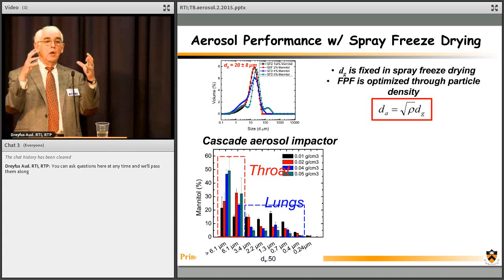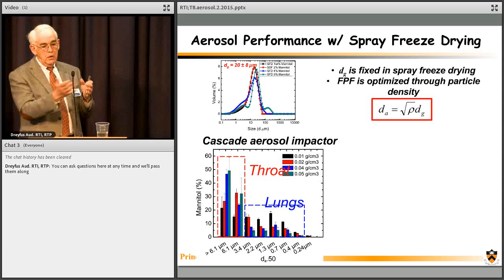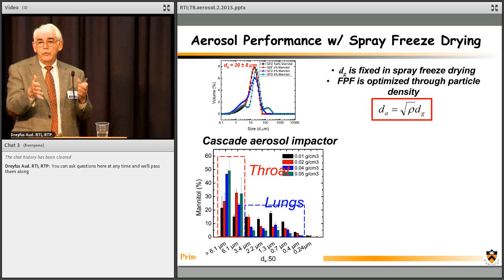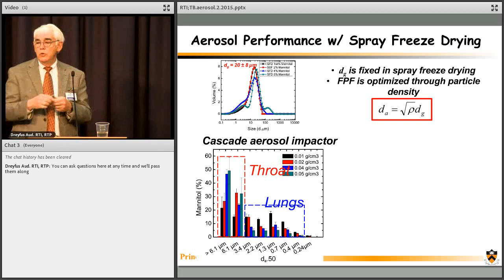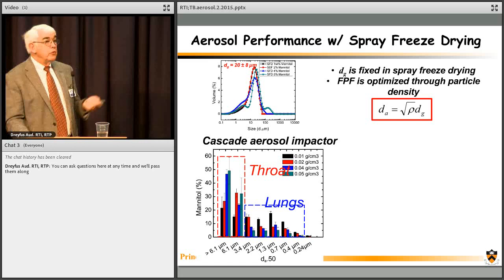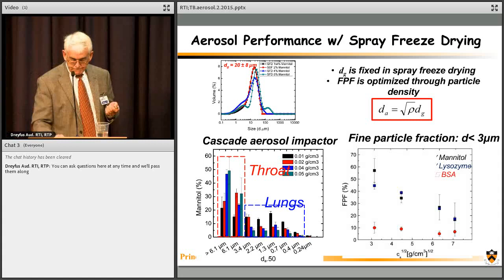So the capture in these airflows is a dense particle with inertia moves across streamlines and hits the surface. But if I make it less dense, it follows the streamlines and doesn't have the inertia to cross streamlines and precipitate. This is widely quoted, but there's actually no literature showing constant size particles of variable density until our data. And so here are the particles.